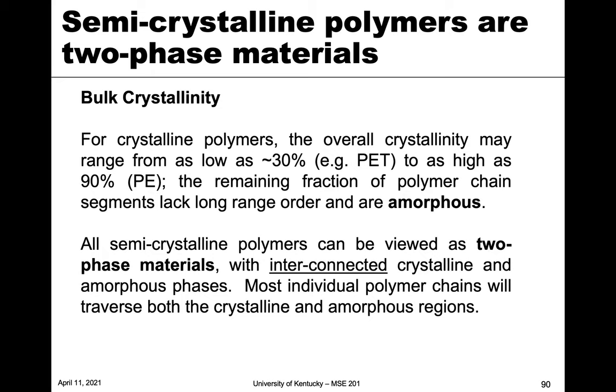The way we think about semi-crystalline polymers with spherulite formation is as two-phase materials when looking at crystallinity. For crystalline polymers, overall crystallinity can range considerably — for PET it can be as low as 30%, and for polyethylene it can be as high as 90%, with the rest being amorphous. We can view all semi-crystalline polymers as a two-phase material where the phases are interconnected because of the chains, but form either long-range order or no long-range order.